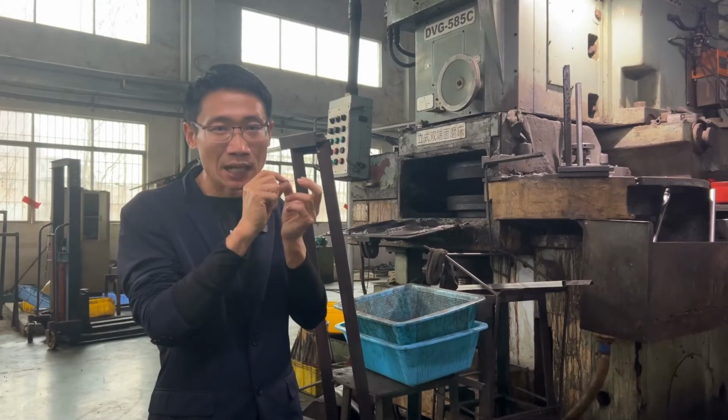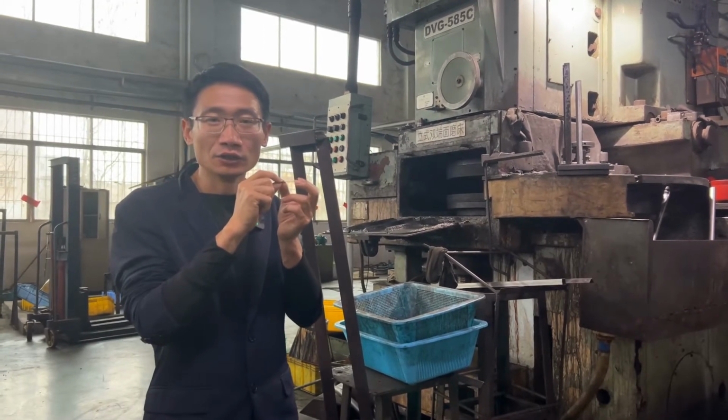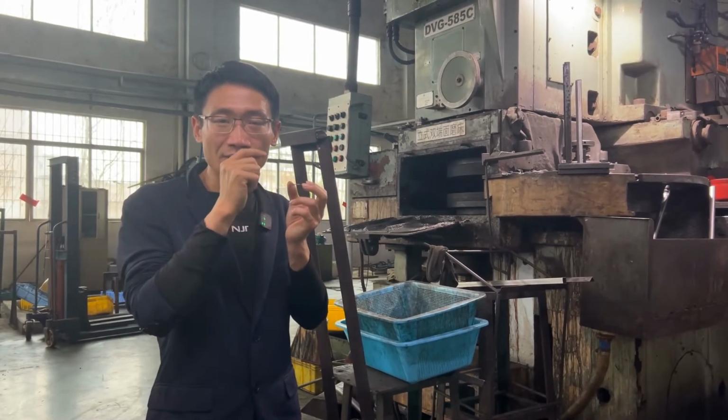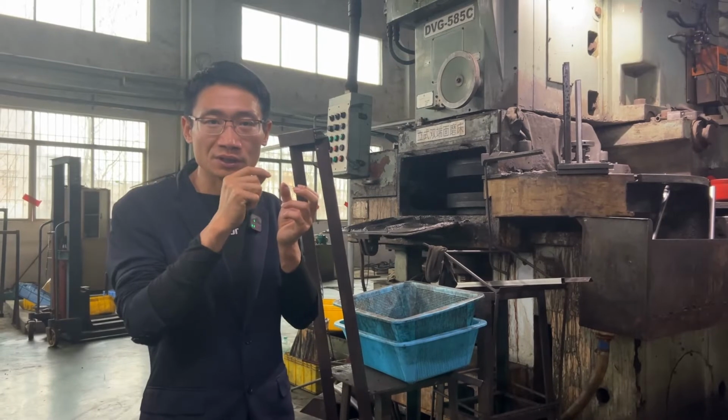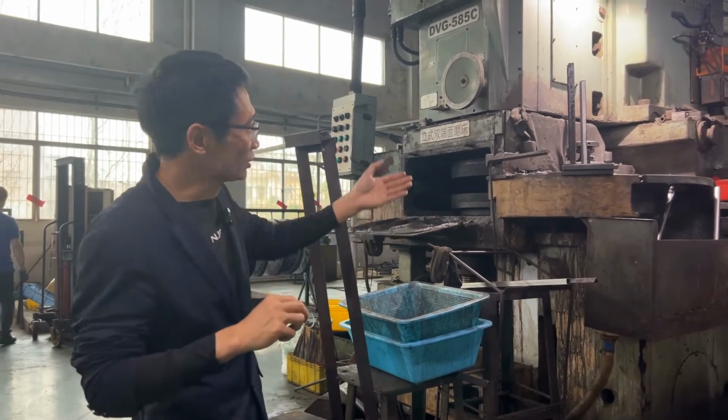Now in the process of finishing the plane of the piston ring. This is one of the most important links in the precision control of the piston ring. After finishing, the surface dimension error of the piston ring should be controlled between 0.01-0.03 mm.